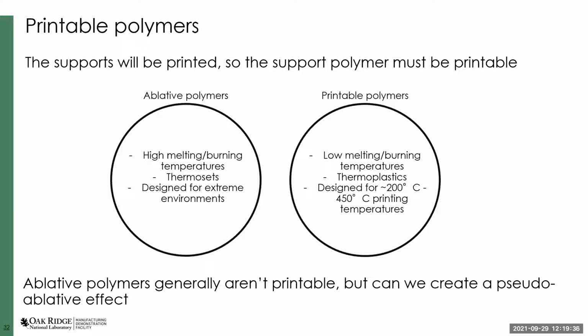Unfortunately, the traditional ablative polymers tend to not be very printable. They tend to be thermosets, which are polymers that are created via a chemical reaction. Think of something like super glue. You squeeze it out of the tube, it reacts, it solidifies, and you cannot process it again. Versus thermoplastics, which are the materials generally used for polymer 3D printing, which can be heated up to soften them, extruded, printed, formed, and then reheated again. So you can cycle them through heat. The Venn diagram of those two doesn't really overlap.